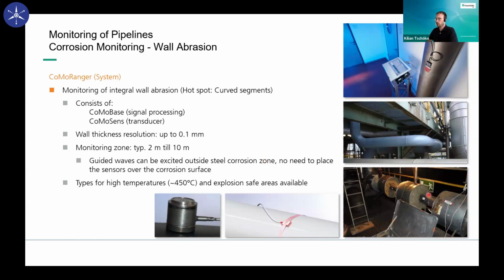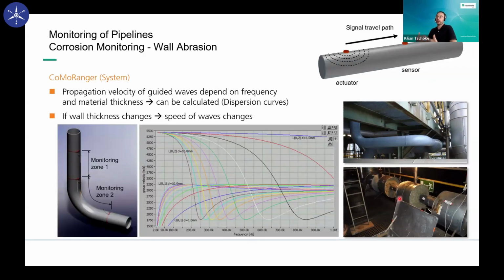As you can see, it can also be under isolation because the transducers are really thin in the best case, but we can also use different techniques. And then if we go into the dispersion diagrams, as you've seen them on the previous slides, we just measure the propagation velocity between the sensor positions, and we recalculate the average thickness of the wall of your pipeline between these 2 sensor positions. This is the easiest case by just using 2 sensors.